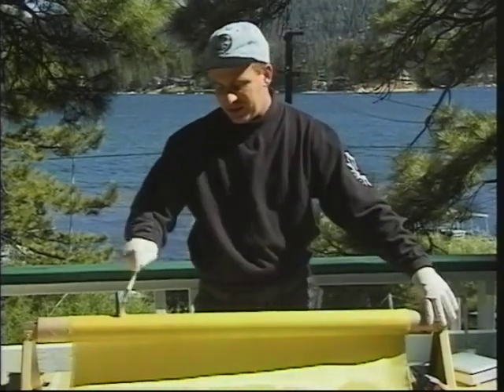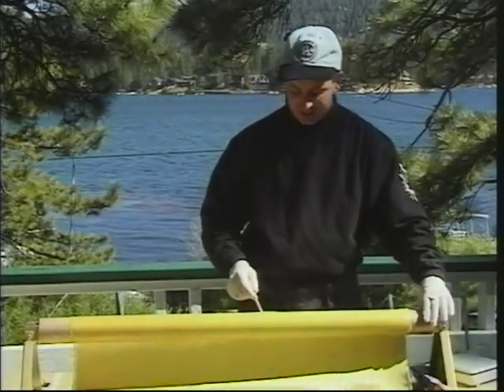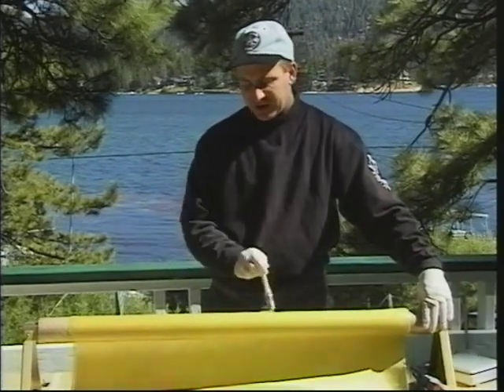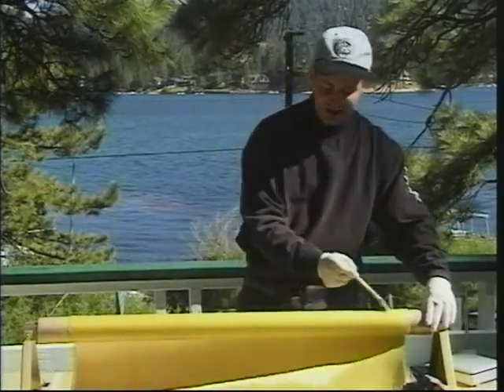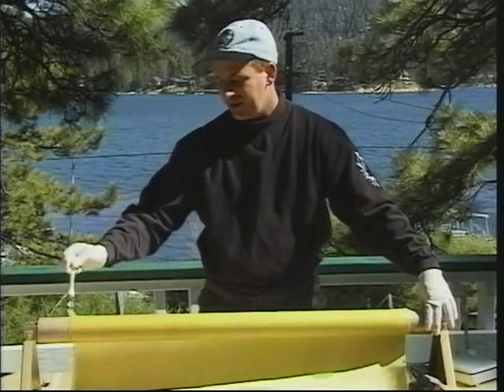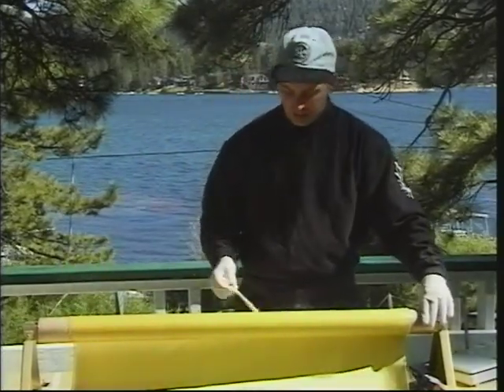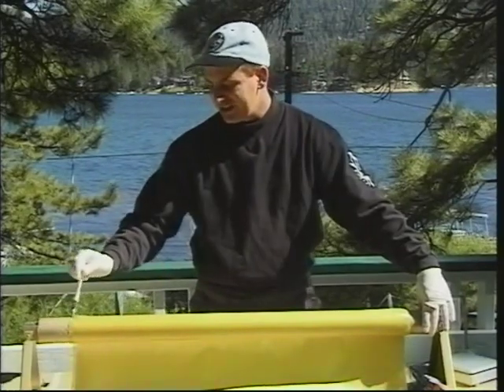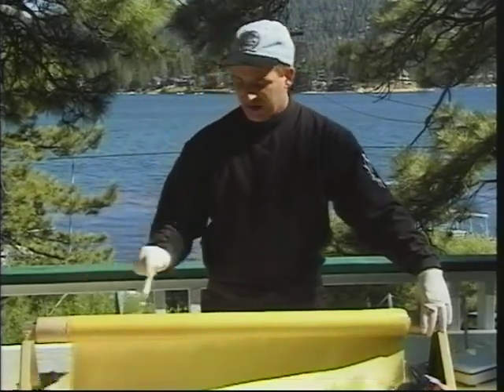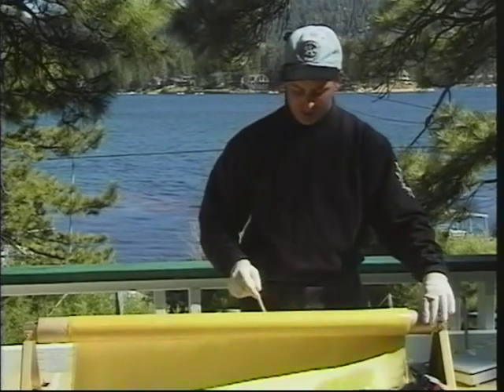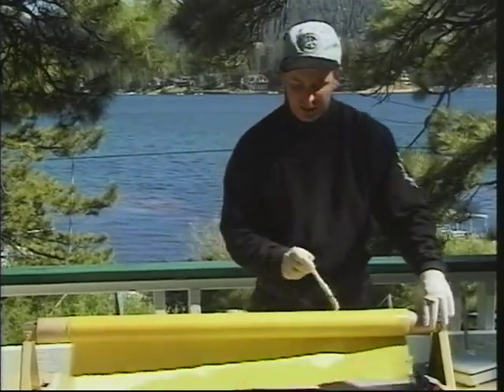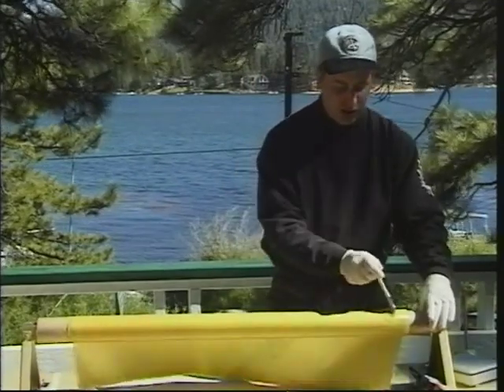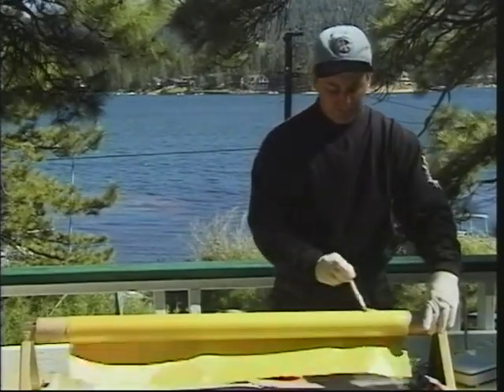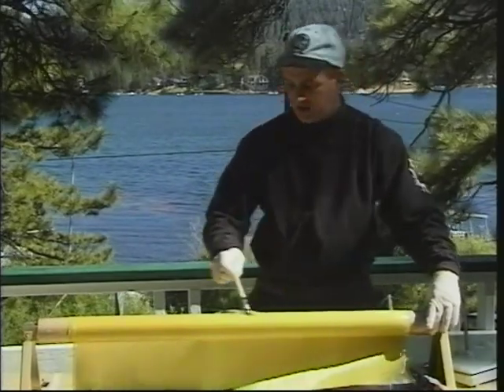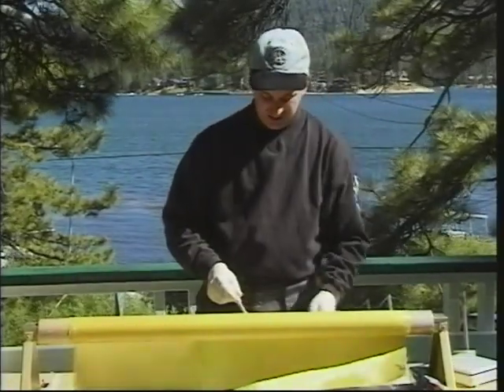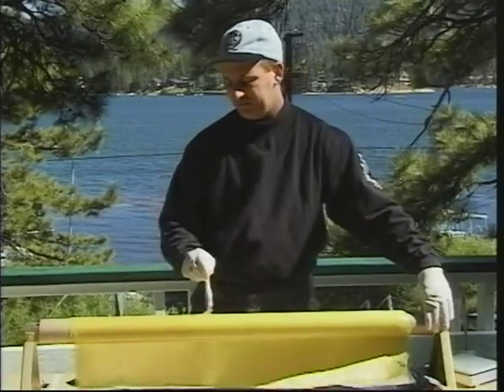I would not recommend using Kevlar for just plain laminate layups. Without the compaction, the Kevlar doesn't achieve the mechanical properties that it's meant to achieve. And all it'll be is basically a tough structure of layers of Kevlar separated by brittle layers of glass, or resin. That's, of course, very brittle, like we discussed earlier. So, if you're going to use Kevlar, use a compaction method. That's really the best way to use it.